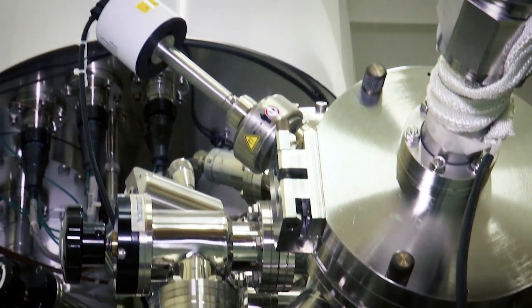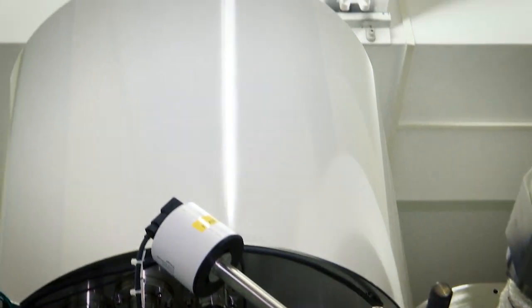This is one of the instruments that we use to determine the quality of our materials. It's both qualitative and quantitative in its results. You can tell what your nanomaterial is made up of—the elemental composition, if there's nitrogen or oxygen or sulfurs, and how much of it—as well as what your elements are bonded to. So your neighboring elements. Is it just sulfur or sulfur next to oxygen?